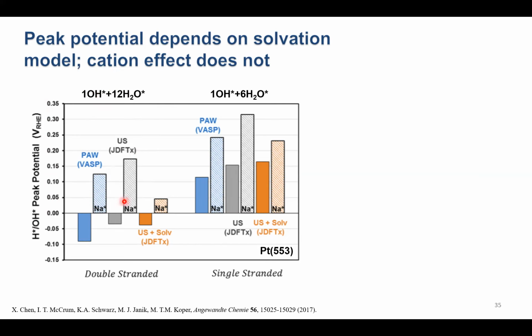What we see is these peak potentials are different. If we add more water, we get a different potential. And so this is something important to keep in mind. And so if we want to be truly predictive in terms of the absolute value of that peak, that would be very difficult to do. What's important here, though, is what we wanted to understand was the effect of the alkali metal cation. And regardless of how much explicit water we include, we see the cation always has the same effect. It shifts this peak to more positive potentials.